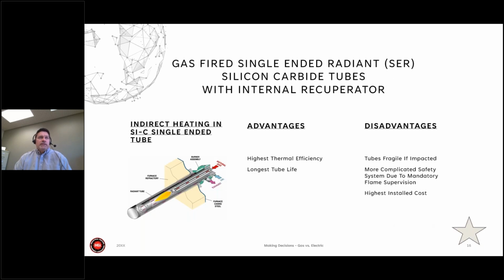If we look at materials selection on the radiant tube, we're changing the alloy radiant tube in this design for a silicon carbide radiant tube, which has a greater heat flux and heat release to the furnace chamber. So it has the ability to reduce the number of burners or radiant tubes that you have inside the furnace. It has the same setup as the single-ended radiant tube, but just with the silicon carbide tube. It would have the highest thermal efficiency and the longest tube life.